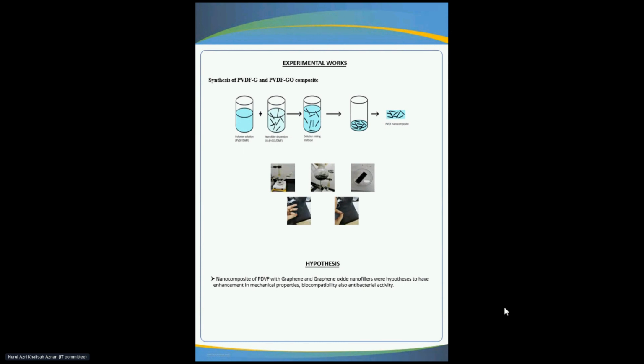So basically, for my work, I'm using a solution mixing technique. PVDF-graphene and PVDF-graphene oxide are being synthesized using two different temperatures and different concentrations of graphene and graphene oxide. This is followed by characterization to study their structural, thermal, and mechanical properties. After that, we'll do cell growth culture for in vitro studies of biocompatible properties.